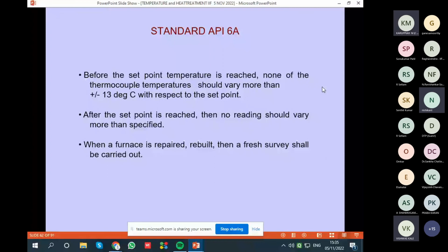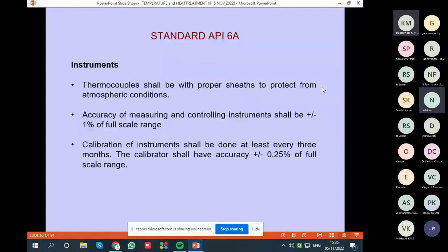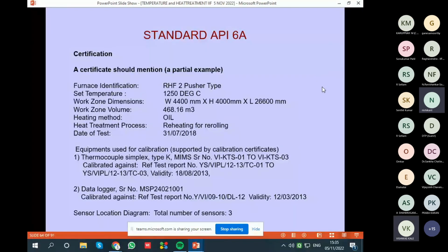And then after standards are done, for half an hour, record the data after the temperature stabilizes. In this case, when the temperature stabilizes at set point, we wait for half an hour and take the temperatures and generate a certificate like this. Mention all the data of the furnace, what are the thermocouples used, what is the data logger used.